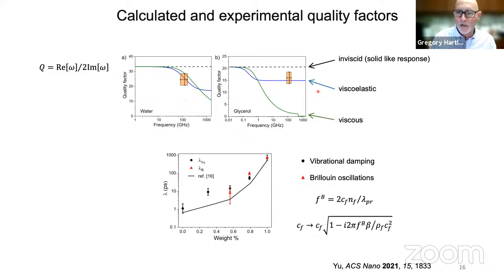Okay? If we go to a very viscous liquid like glycerol, then you can see that there's a clear difference now between the predictions of models with viscoelasticity and without viscoelasticity, and that our experimental results match the viscoelastic model quite well. They don't match the inviscid model where you leave out viscosity. So maybe a better way of doing this experiment is to just take our quality factors that we measure and then use the equations to fit to determine a relaxation time. And so that's what's done here.